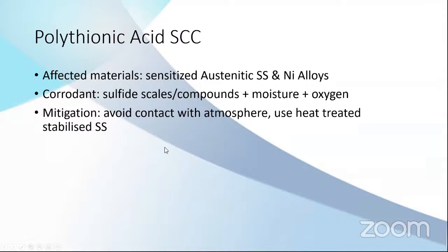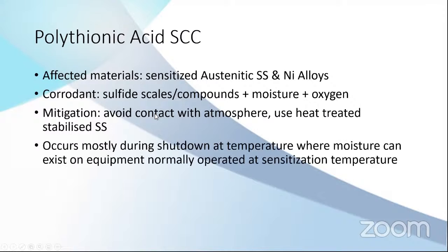So the mitigation is to avoid contact with the atmosphere, so you don't get moisture and oxygen, or you use heat treated stabilized stainless steel, the one that I said before, the niobium and titanium addition stainless steel. This happens in a refinery mostly, where a lot of sulfur is getting treated, for example, in the boiler where you're using high sulfur fuels.